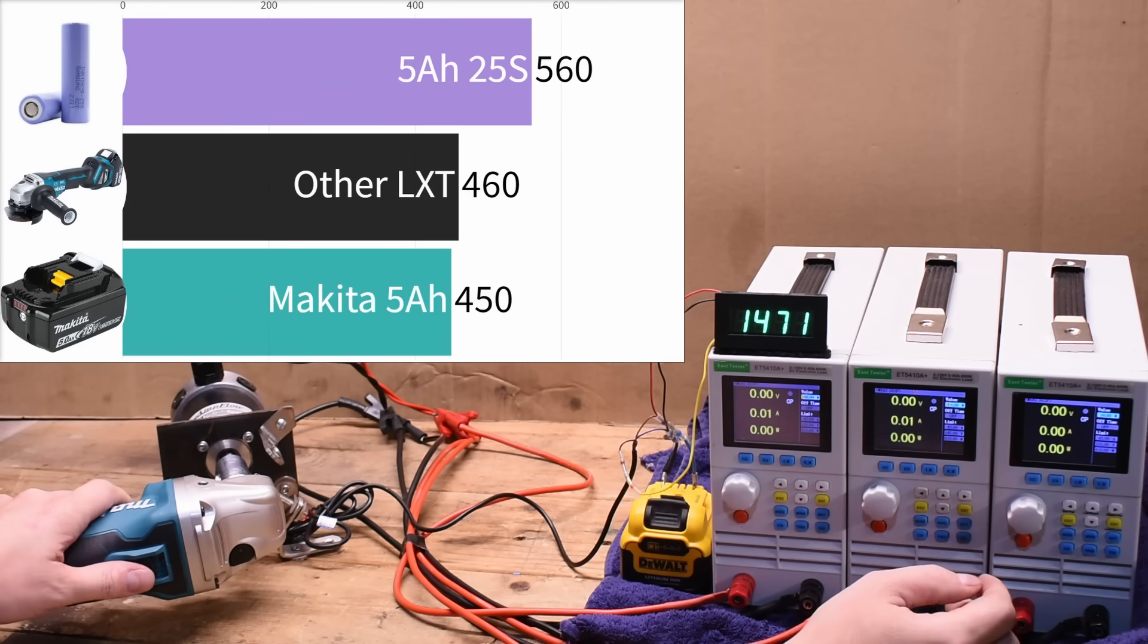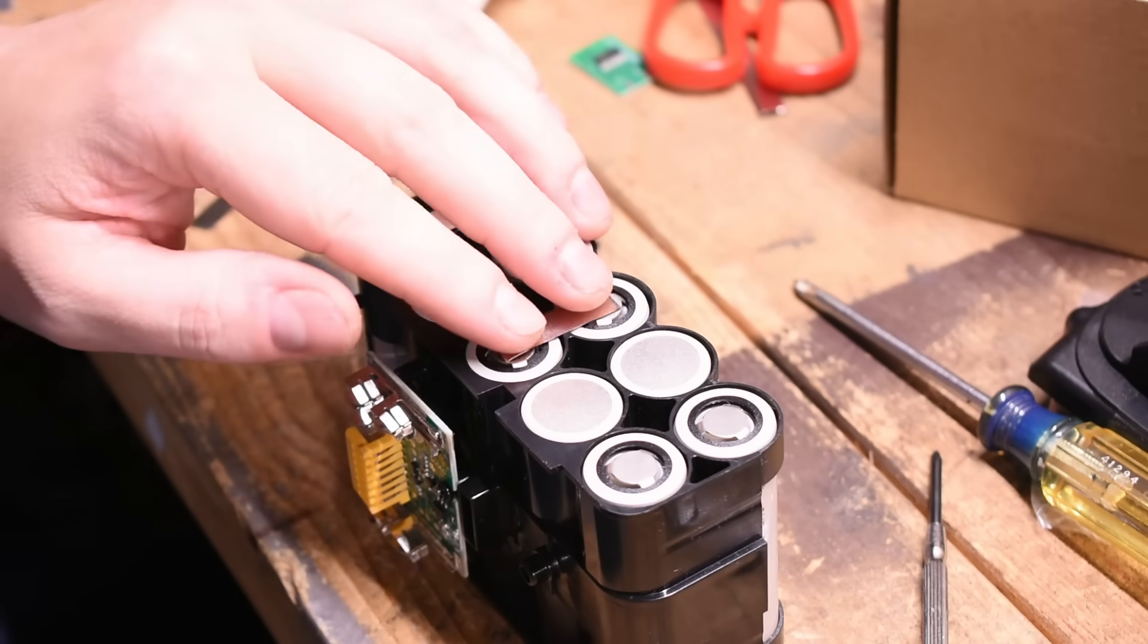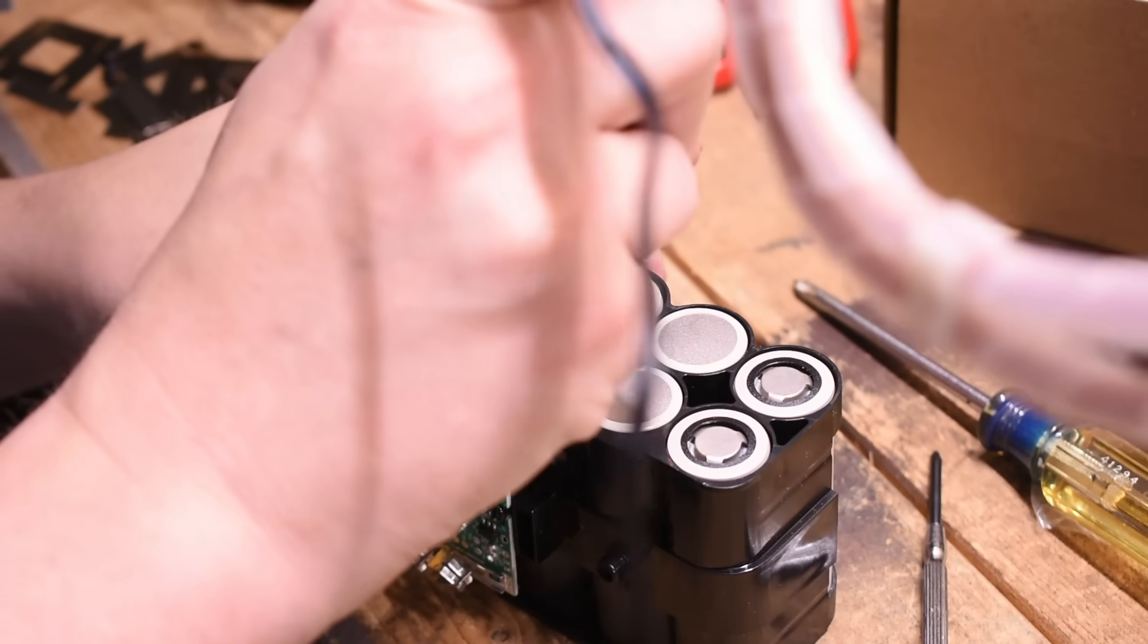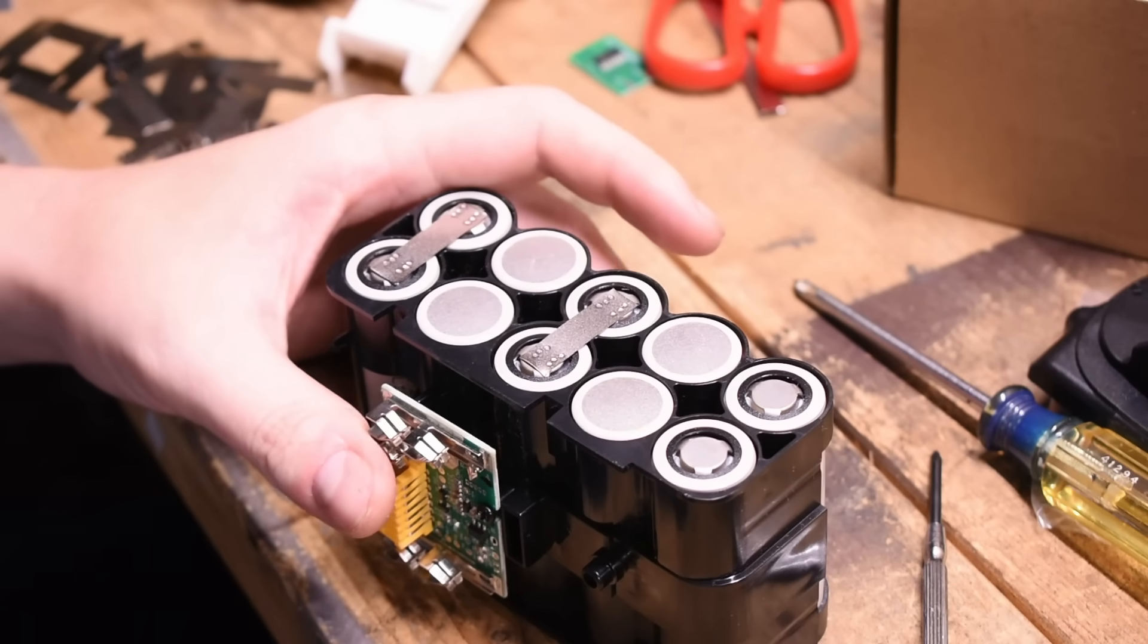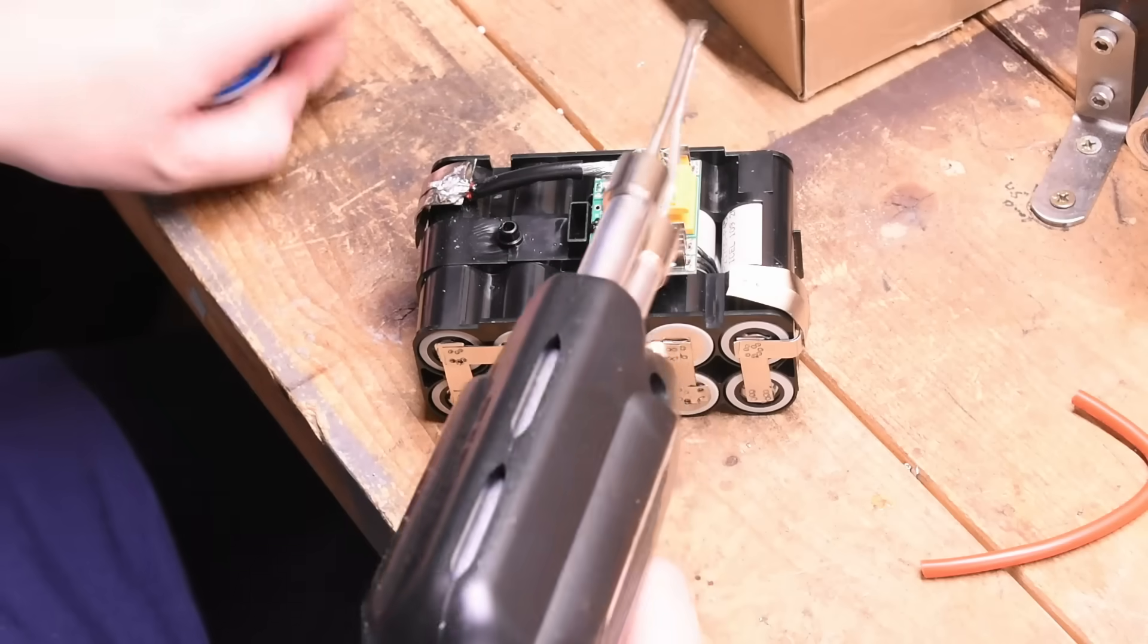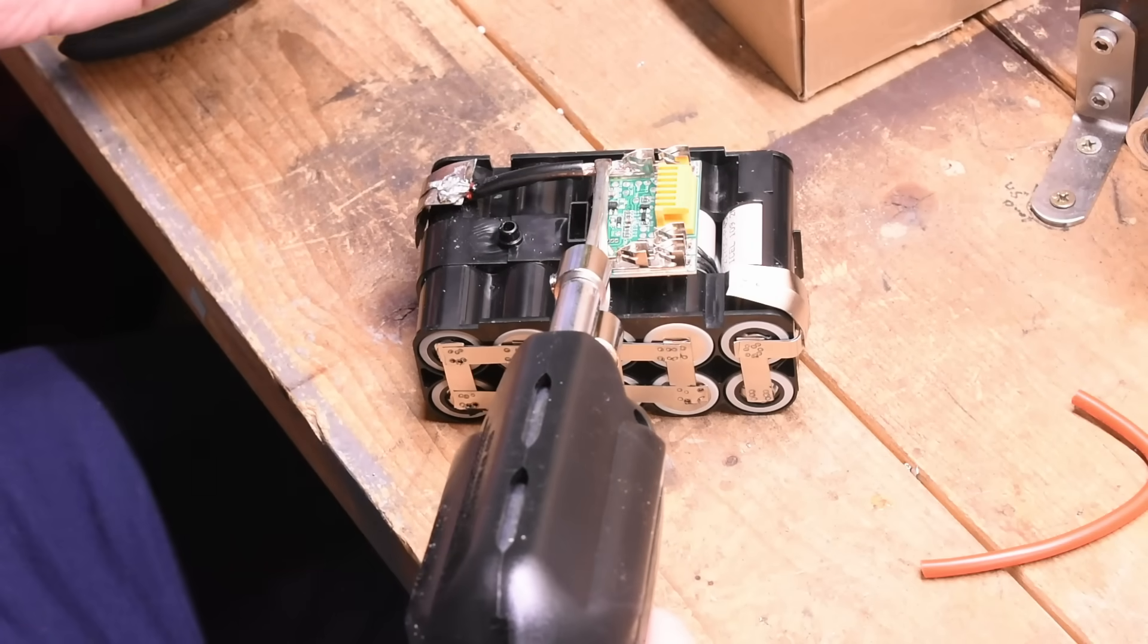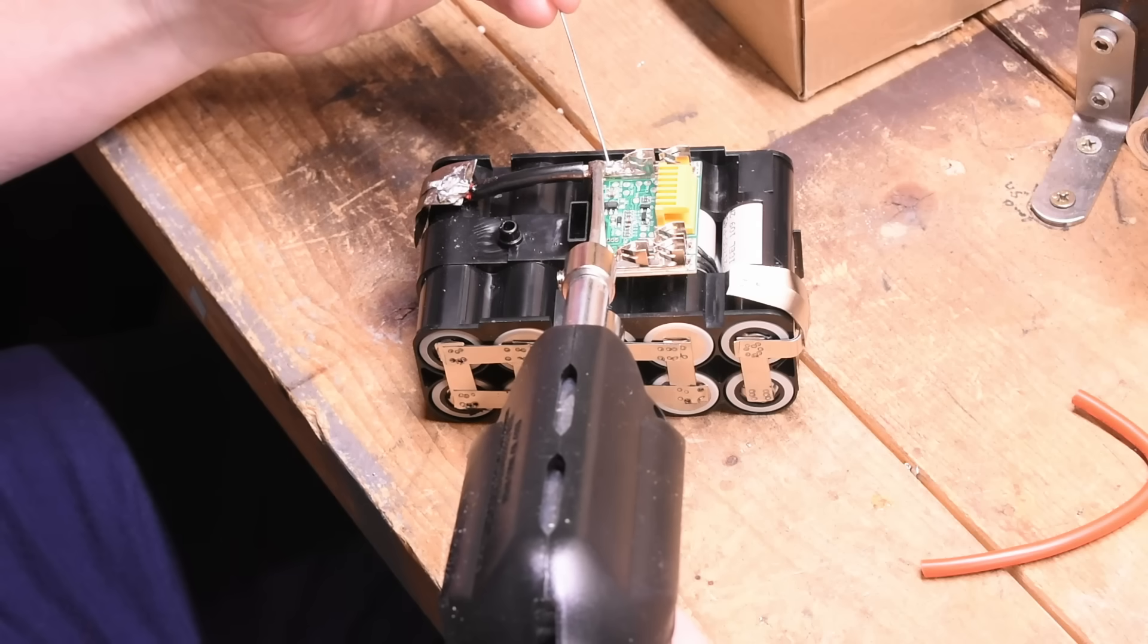Which makes you wonder, can we do even better? We used eight strips of that 0.25 millimeter nickel over each battery cross-section, two overlapping each other, and welded that all down to double up and better prevent what happened last time. Then routed these strips in a way that we could use 10-gauge wire without an obstruction in the battery case, which required a 260-watt soldering iron to get everything to warm up and play nice together.